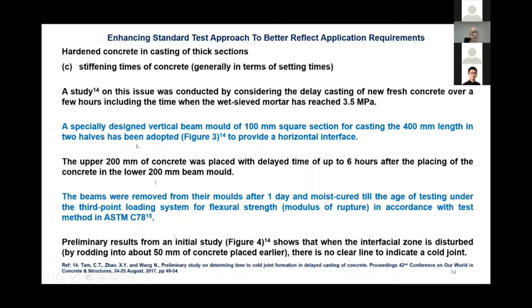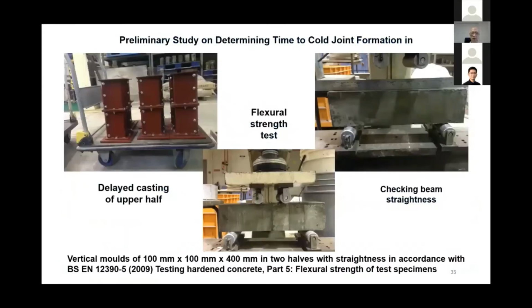So we now designed a vertical beam mold, 100 mm square, 400 mm long. The upper 200 mm will be cast later, and the lower 200 mm will have an interface. That interface can be used to study what we can do with it. After we remove the beam after 1 day, we cure it and then we test. Now this is our vertical mold that we made, quite expensive. And this is the beam that we test in third point loading. You can see here, the student had to check whether, because we are casting the beam vertically, we are sure we get a flat surface. So this ruler is there to look at the gap, whether it looks reasonable or not, before we do the actual flexural test.